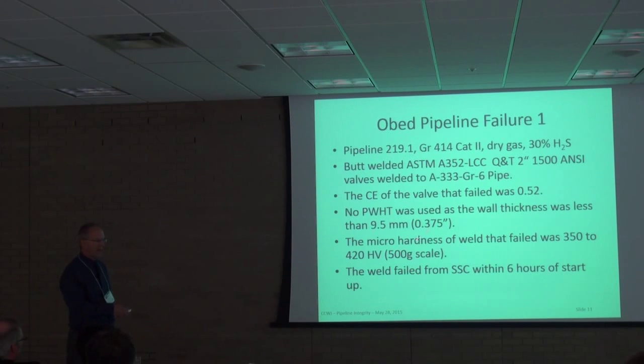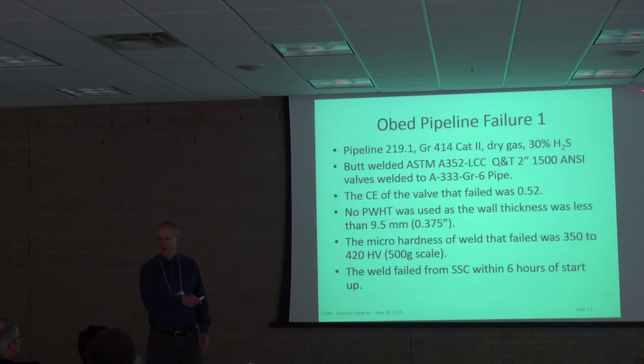And the other lesson in here is that this is a dry line. This line was expected to be thoroughly dry. So if you have no water, you shouldn't have had sulfide stress cracking. But there was just enough trace water, combined with the right circumstances and residual stress, that it cracked and failed catastrophically.